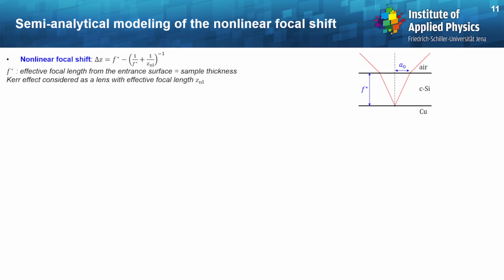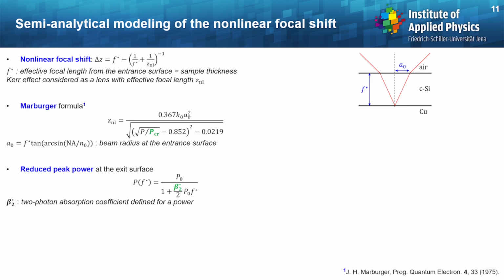So we want to evaluate theoretically the nonlinear focal shift delta Z, which is here. It reads this equation here, where f star is nothing else than the sample thickness, and the ZNL parameter corresponds to the Kerr effect, which is considered as a lens. With this, we can evaluate ZNL by the Marburger formula, where we have a first free parameter, which is a critical power for self-focusing.